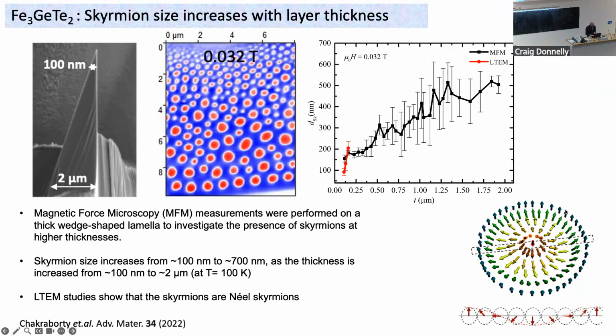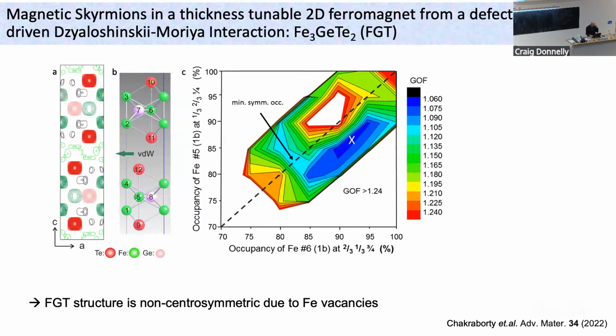And just to remind you, a Néel-like skyrmion is a small object, typically formed in arrays, where the magnetization rotates from an up direction on the outside to a down direction on the inside, and you see the magnetization rotates parallel to the radius of this object all the way around. This is called a Néel skyrmion, and it's a topological object. Here, the size is changing because of dipole-dipole interactions. Anyway, I want to say this.